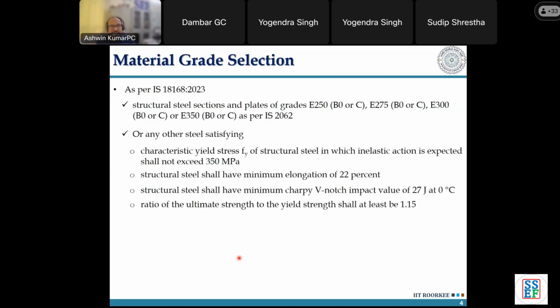Another clause inside the same code says that if any other steel is being used other than E250, 275, 300 or 350, you have to ensure that the nominal yield stress should not be greater than 350. So currently the code in a high seismic region does not allow you to use more than a 350 grade of steel, right? The second thing is that any other class of steel, not of the grades mentioned above, should have a minimum elongation of 22%, which means you do a coupon test as per IS 1608 or ASTM E8. You mark the gauge length location, and then, once the fracture has happened, you measure the change in length relative to the original gauge length. That percentage elongation should be more than 22%.